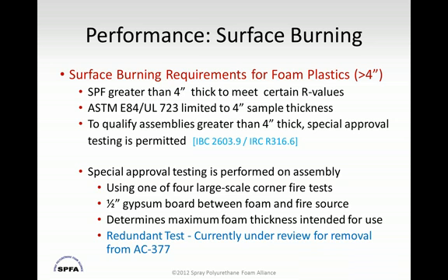And this has been repeatedly done for a lot of foam products over the past 5 to 10 years. They all use a 1/2-inch gypsum wallboard between the foam and the fire source, and this has been used to determine the maximum foam thickness intended for use. If you look at this type of testing we've been doing, the half-inch gypsum is already a 15-minute thermal barrier. And what we found is that none of these particular assemblies using foam have failed, as long as they pass the E84 test at 4 inches or less. None of these have failed.